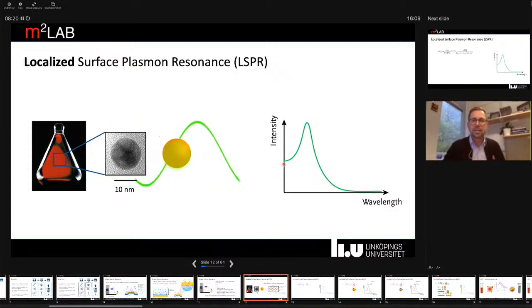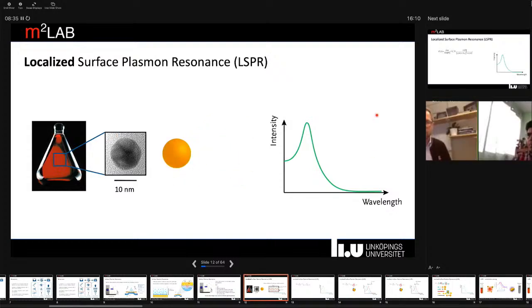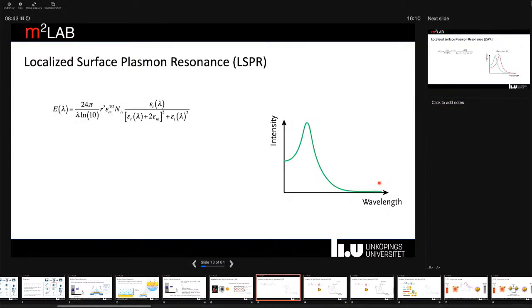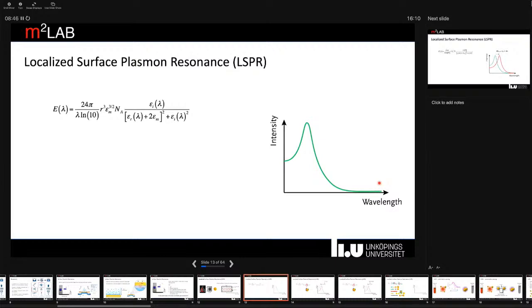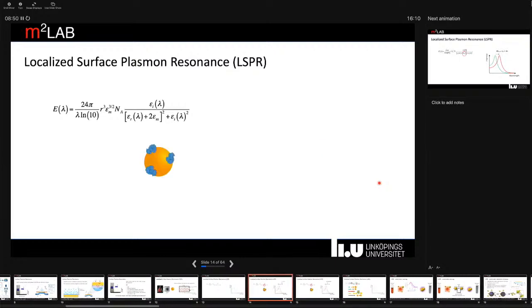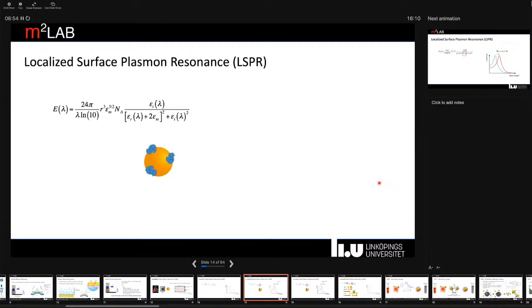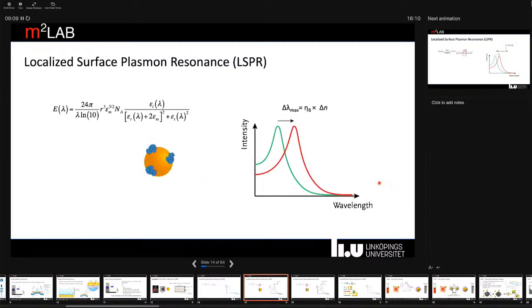And we can see this as a quite pronounced extinction band in the visible wavelength range. For particles this size, this occurs in the green wavelength range, which makes the suspension of these particles look red. As you can see, there's literally no interaction with light here at this wavelength. And the position and intensity of this LSPR band depends, just as in the case of SPR, on the dielectric properties of the vicinity of the particles. So if we, for example, immobilize or adsorb some sort of biomolecules on these particles, we'll obtain a change, typically a redshift, in the plasmon band.